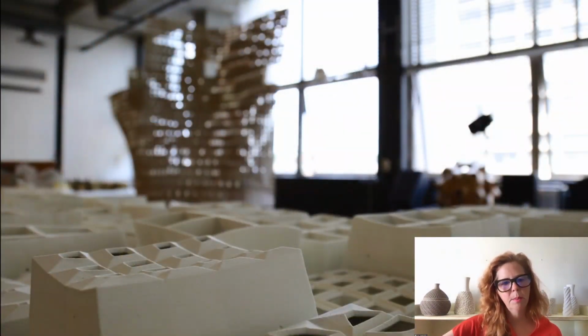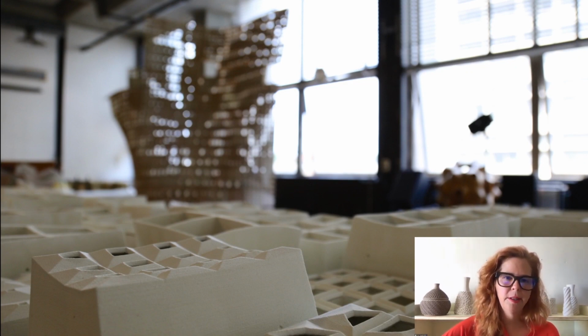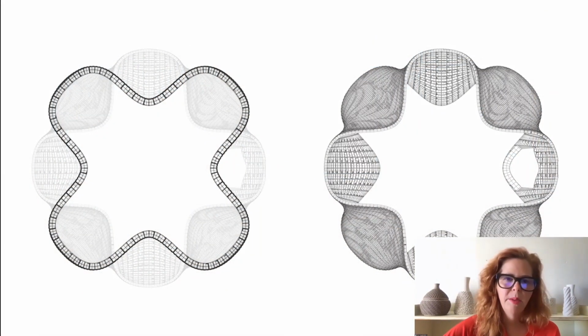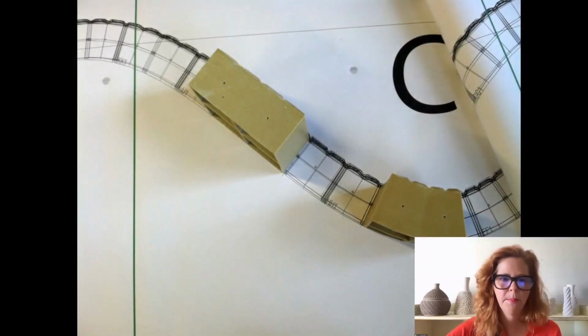The tiles are printed either 1 or 2 at a time in a traditional Z-Corp 310 printer. So here you can see some of the deeper tiles at the bottom of this image. They're about 4 to 5 inches deep, and they have holes in them for mechanical fastening. And as we move up to the top of the pavilion, the tiles become much thinner, only around 1 inch deep, so we could print more tiles at a time, but also reduce the weight of the structure as we moved up.